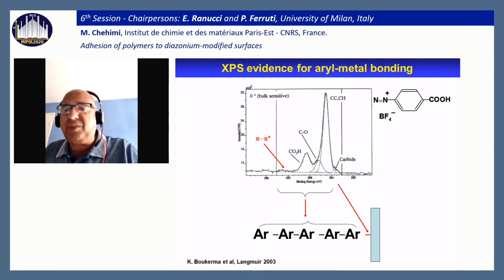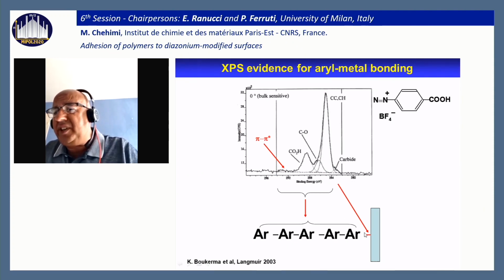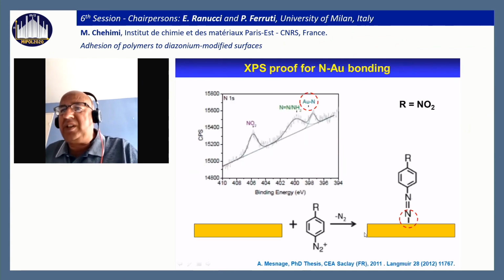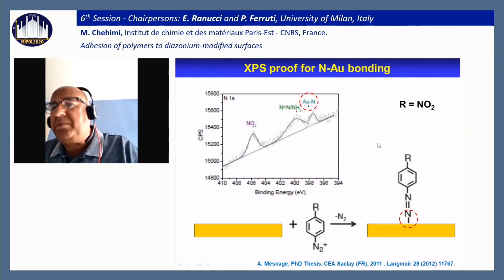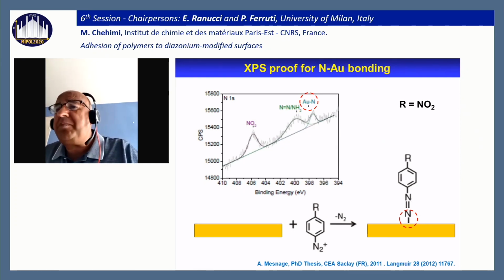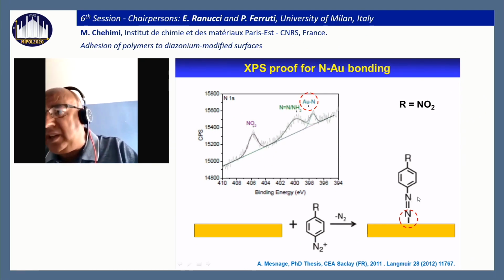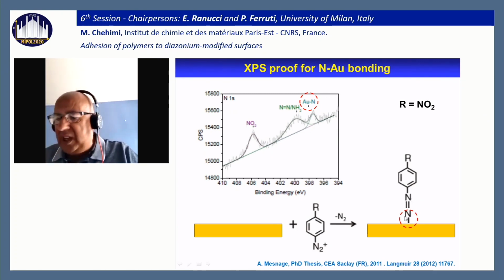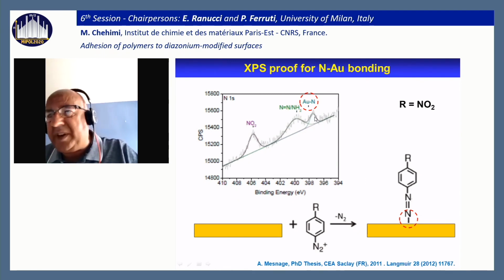By XPS, we have demonstrated the existence of carbide at the interface with metal. Other groups from the South of Paris have demonstrated the bond between gold and diazonium salt without dediazoniation of the salt, without removal of the N2. This can be proved by XPS. We can see the nitrogen here.